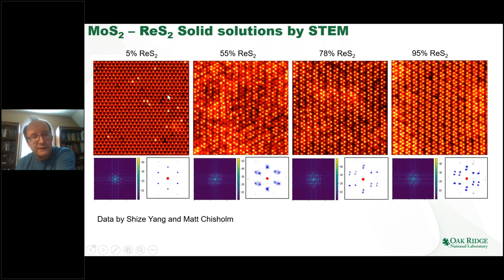If you start and the system is, you can see a clear ordered six-fold lattice. If you start to increase the amount of rhenium in the system, you start to see that the number of bright atoms goes up. And you also start to see this kind of crisscrossing lines, which is the signature of the first order phase transition. So if you take these images and do the Fourier transform, you can see what you expect for the first order phase transition.